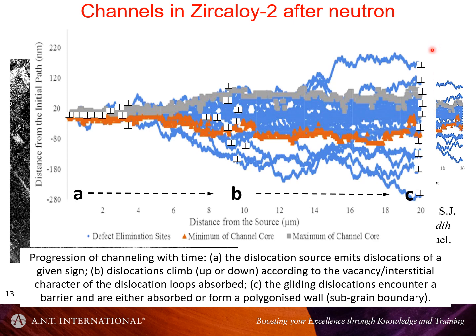And if this was butting up against a grain boundary, we'd have an array of dislocations which are very close to the boundary. And some people might mistake the tilt you would see of the crystal from these geometrically necessary dislocations as a stress, but it's not. It's actually a low energy configuration when the atoms of the dislocations are arranged like this. It's not the same as taking a simple elastic stress.